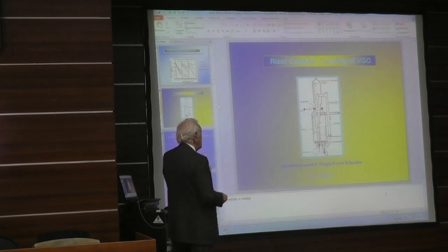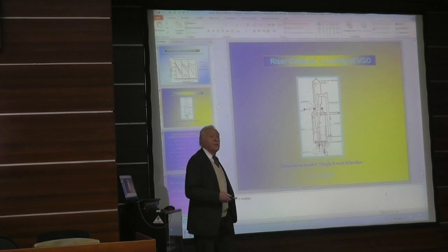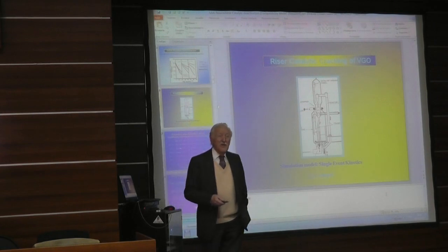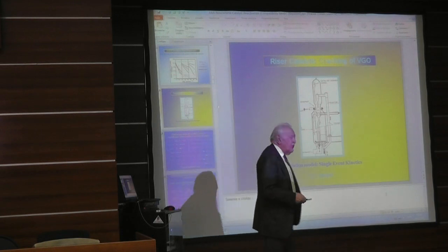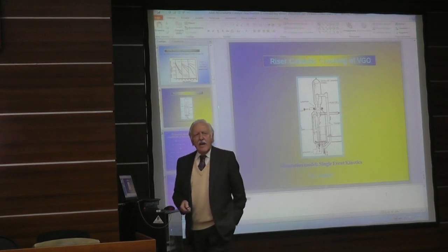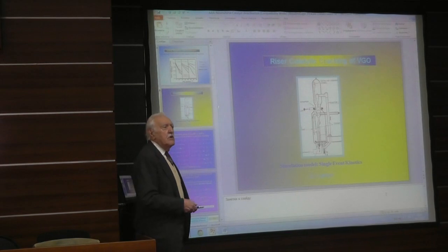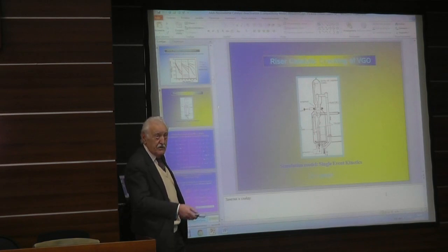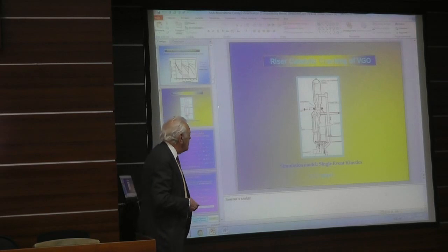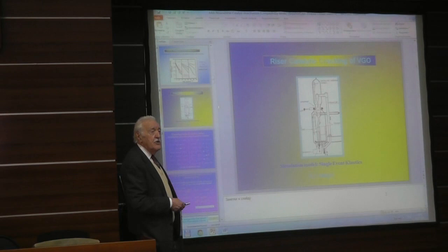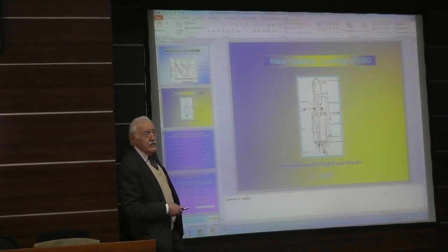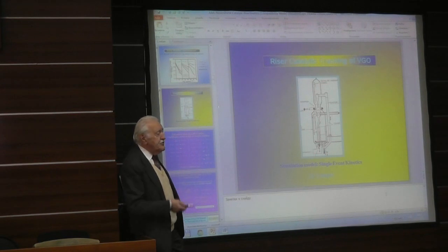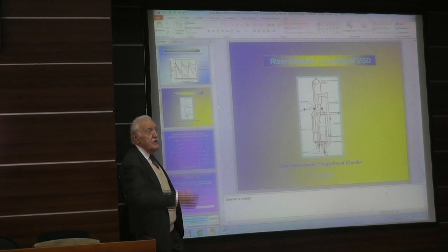Okay. This is the most well-known example of the effect of catalyst deactivation. You know, before 1940, the cat cracking of vacuum gas oil to produce better, lighter fractions, gasoline, diesel, kero, that was done by cat cracking. And before 1940, that was done in a fixed bed, that was the Houdry process for cat cracking, but it deactivated like crazy, and they had to switch very, very frequently to regeneration, etc.